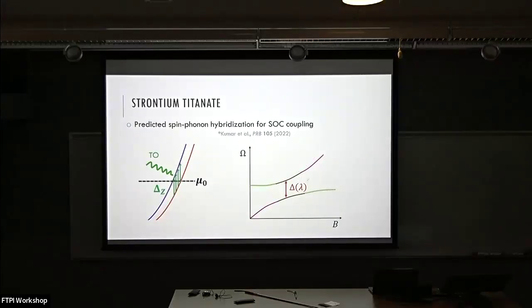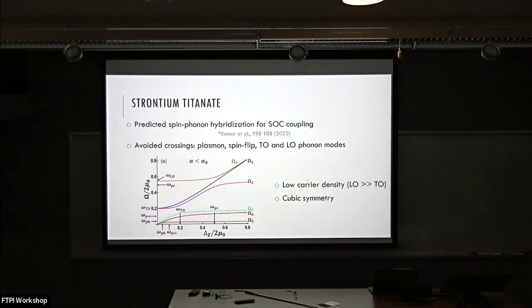And now, if there is this spin orbit kind of coupling, then there's been a recent prediction that this leads to spin phonon hybridization. So if you split the Fermi surface with a magnetic field, you should be able to hybridize with these spin flip modes. So there's going to be some sort of anti-crossing. If this is a spin flip mode and this is the TO mode, you're going to have a change of character at some characteristic field. Now this is the actual prediction for the low carrier density limit. And there's a lot of modes. So this includes LO, TO is here, and then this is a plasmon and two spin flip modes, and they all hybridize basically. So if you have this coupling, you're going to get this quite complicated hybridizations.